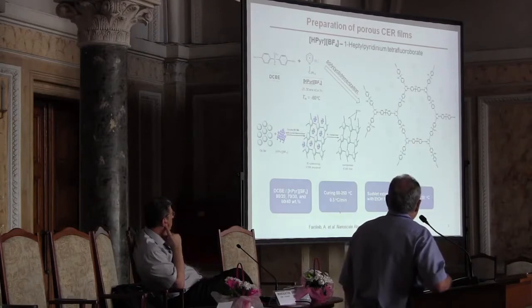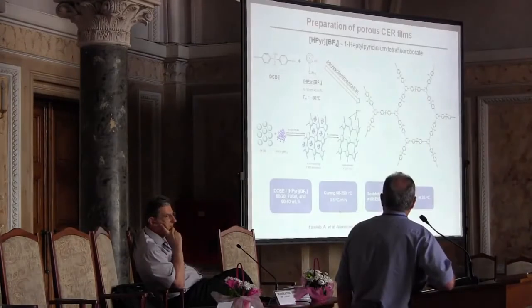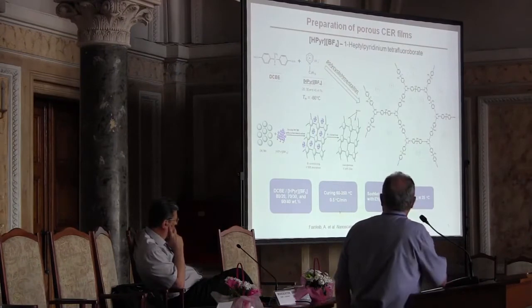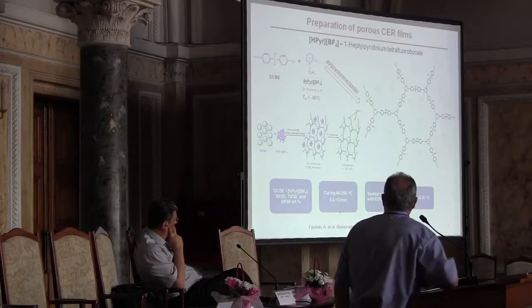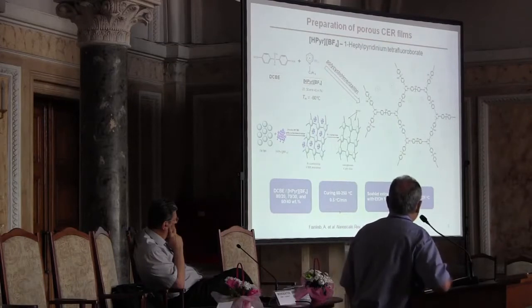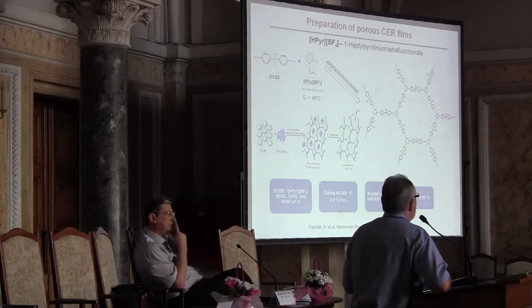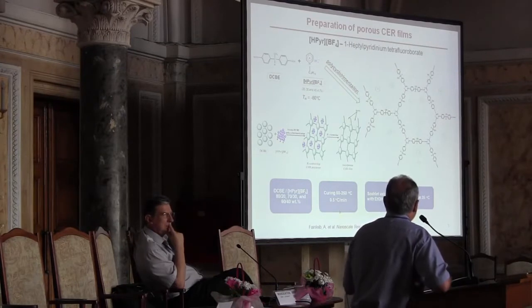So how do we prepare the porous cyanate ester films using ionic liquids? One was 1-heptyl-pyridinium tetrafluoroborate as ionic liquid. Cyanate ester resin was polymerized in the presence of ionic liquid, and we have this high cross-link density network keeping inside ionic liquids, and after complete conversion of monomer into the polymer network, we removed ionic liquid by extraction.